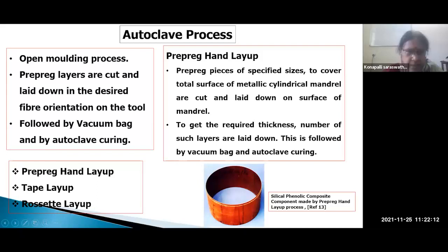So here it is pre-preg hand layup we can do, tape layup we can do, and rosette layup we can do. Pre-preg hand layup is basically for cylindrical sections. For making this figure, it is making cylindrical sections. You cut the fabric in specified dimensions, and lay it down on the surface of the cylindrical mandrel. And the number of layers you have to put to get the required thickness. Then make the vacuum bag, put it in autoclave and get it cured and machined.